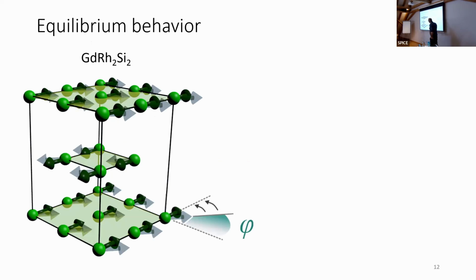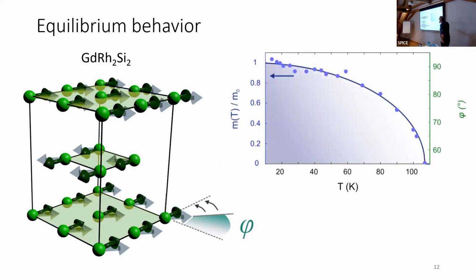Now what I've drawn here is transparent and solid spins in one layer, and the same thing in the opposite layer, just pointing in the opposite direction, and again up here. And I've already drawn this angle, which will become obvious why in a minute. And when we heat up this material, its magnetization, well, its ordered moment or its order parameter weakens until it goes to 0. Another key feature is this curve here, which is this angle here.